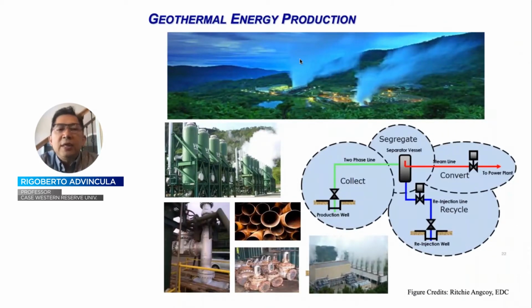Another industry that's quite interesting, with very challenging needs, is geothermal energy. As you can see here, there is high temperature and a corrosive environment. Not so much high pressure, but actually pressure plays a very important role in the presence of scaling and corrosion. This needs to be protected. That is, the assets will degrade much faster because of the Arrhenius law with regard to corrosion, or the mineralogy and the high brine condition, not to mention steam or high temperature three-phase fluids. So protecting them, whether you use the best alloys or different types of coating methods, has to be part of the project and operation.